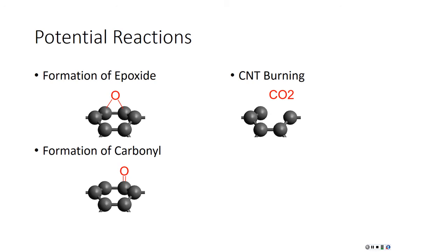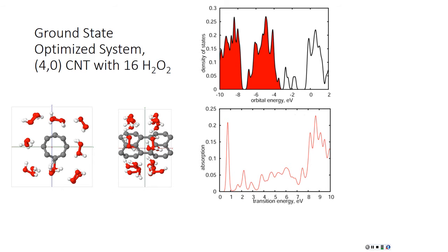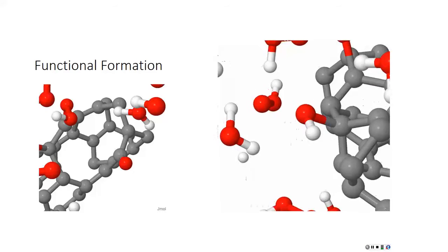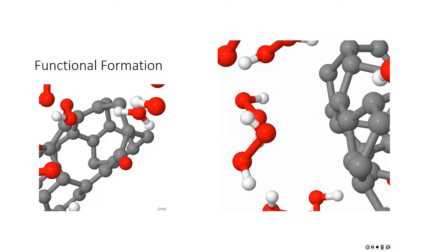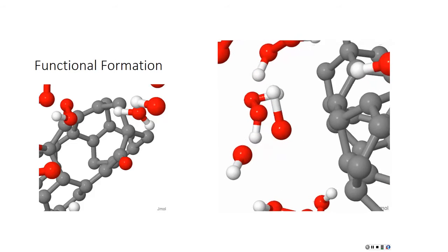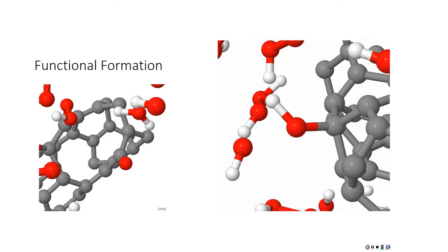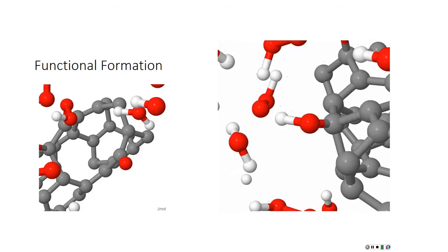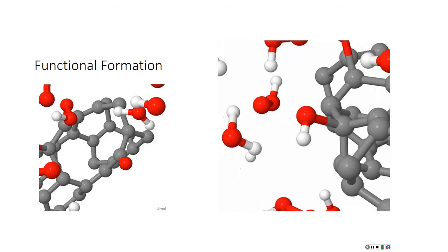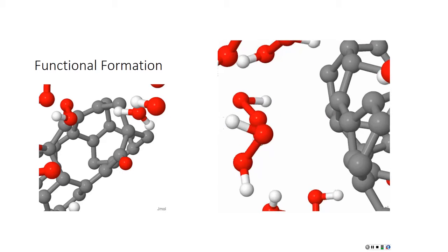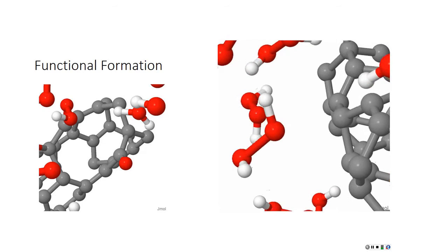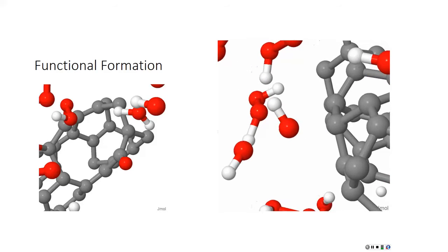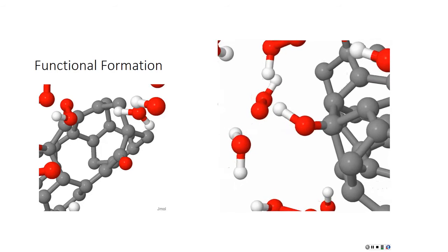So we looked at this unit cell here, which is 2 units of the carbon nanotube long, and it has 16 hydrogen peroxides around it. And we ran a dynamic simulation for that. And one interesting part here, you can see the reaction between the hydrogen peroxide, one of the pathways here. The hydrogen peroxide breaks, and a hydroxyl group goes and forms with the nanotube, which is one of them that I did not expect to happen. And in this still frame here, it's kind of hard to see, but the 6-member ring on the carbon nanotube was functionalized with 3 different oxygens, and it actually broke and created a hole on the nanotube without dissociating a carbon off of the nanotube.